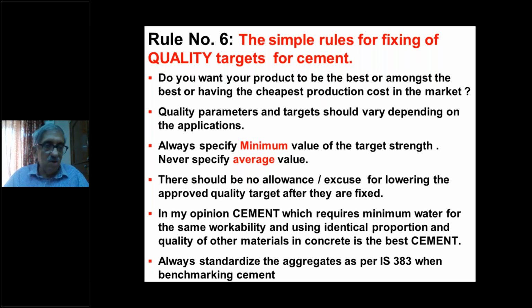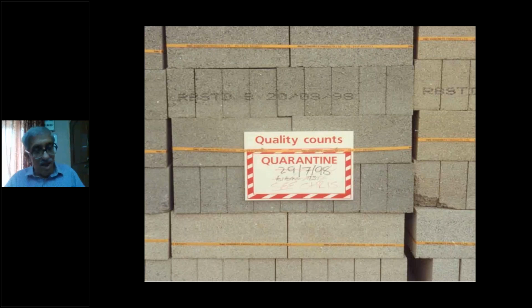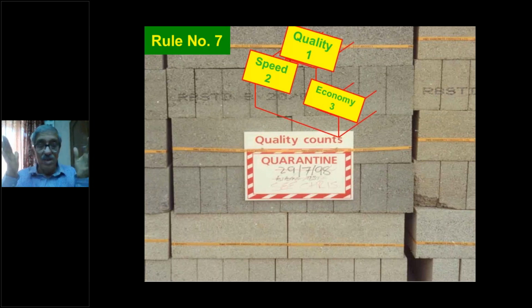It's very, very important. You'll be surprised to note that when we were doing testing of cement, we found that the standard sand, which used to come from Ennore and had to have a particular grading as shown by the standard, was not having that grading. So in India, we are producing standard sand that is not of standard, or substandard standard sand. So we have to convert the sand in such a way that we use a real standard sand in our laboratory.